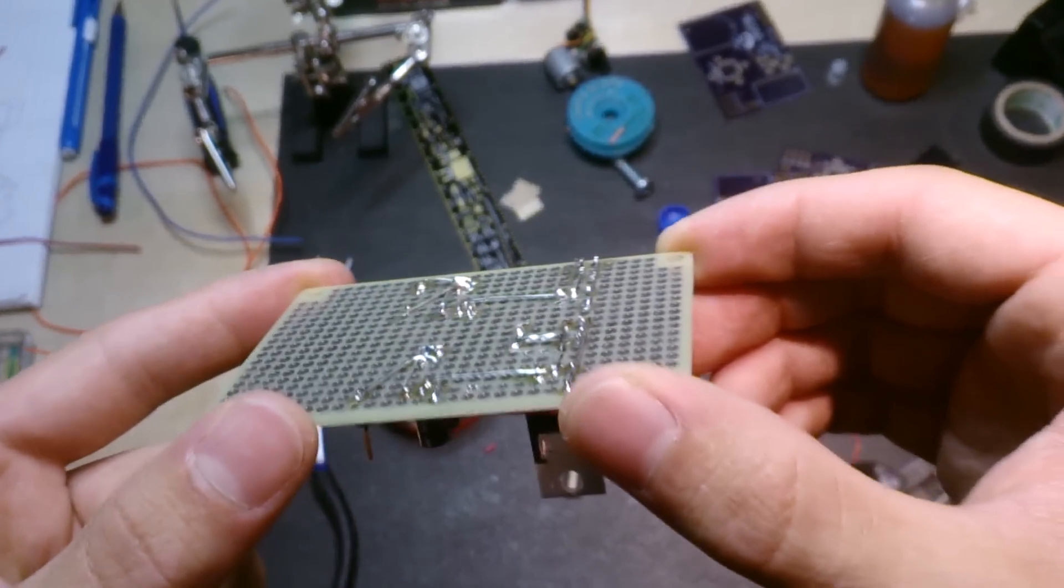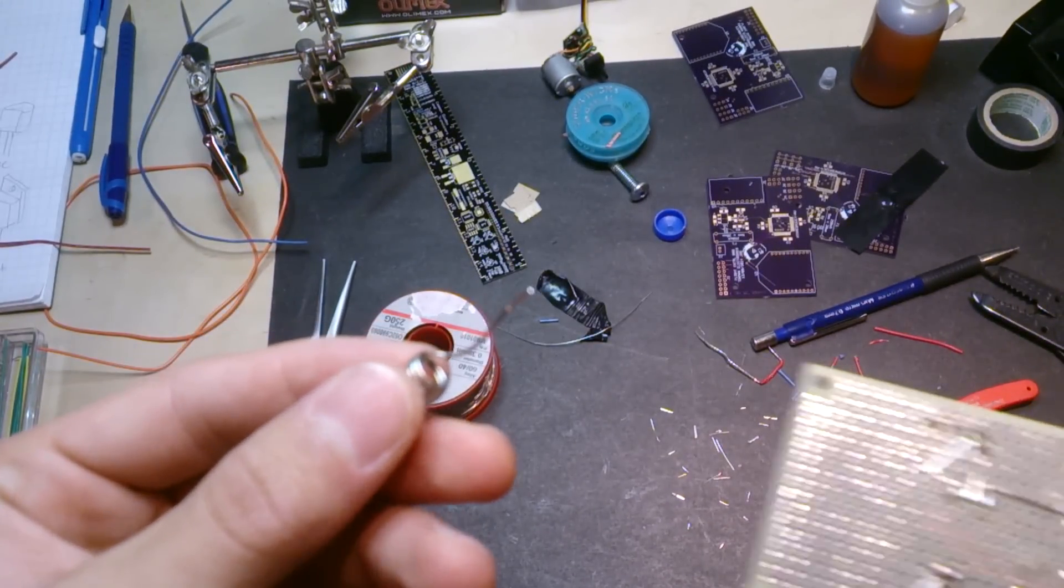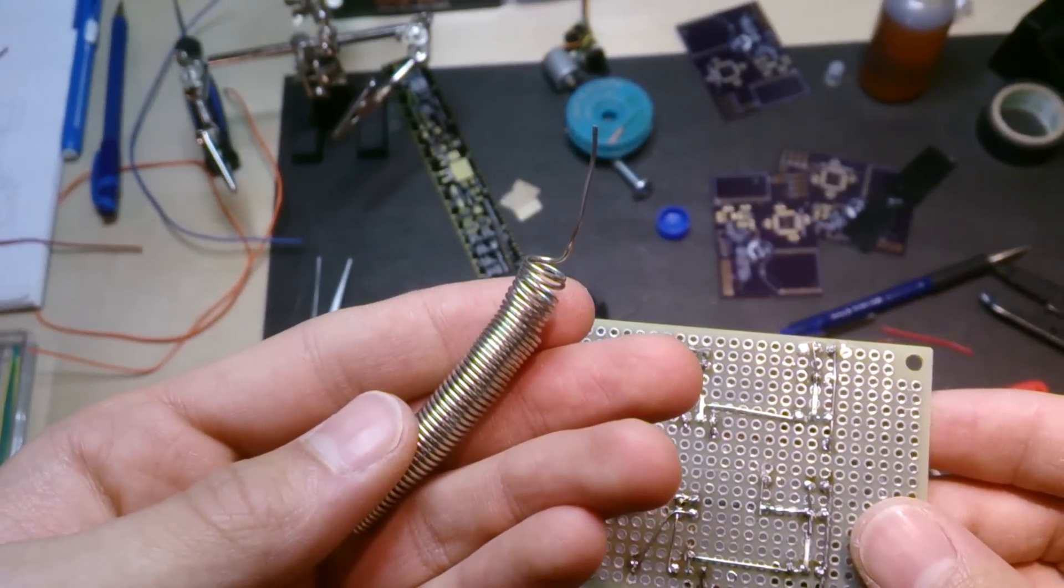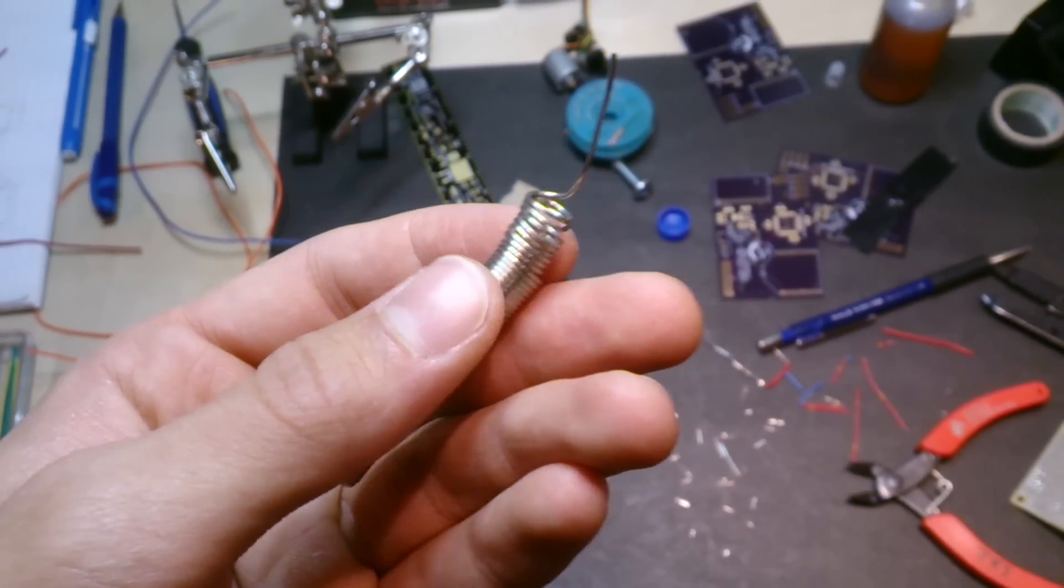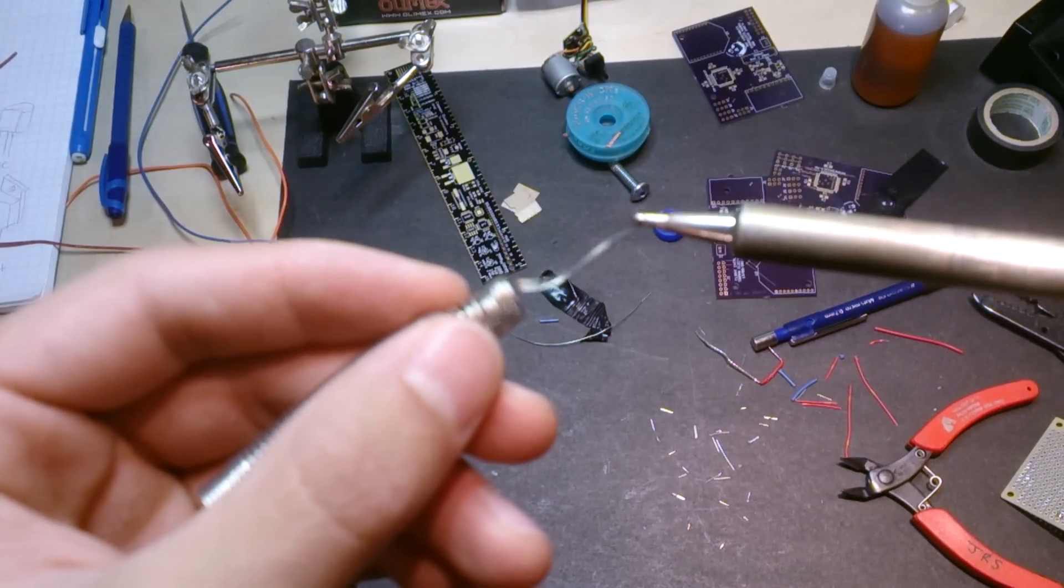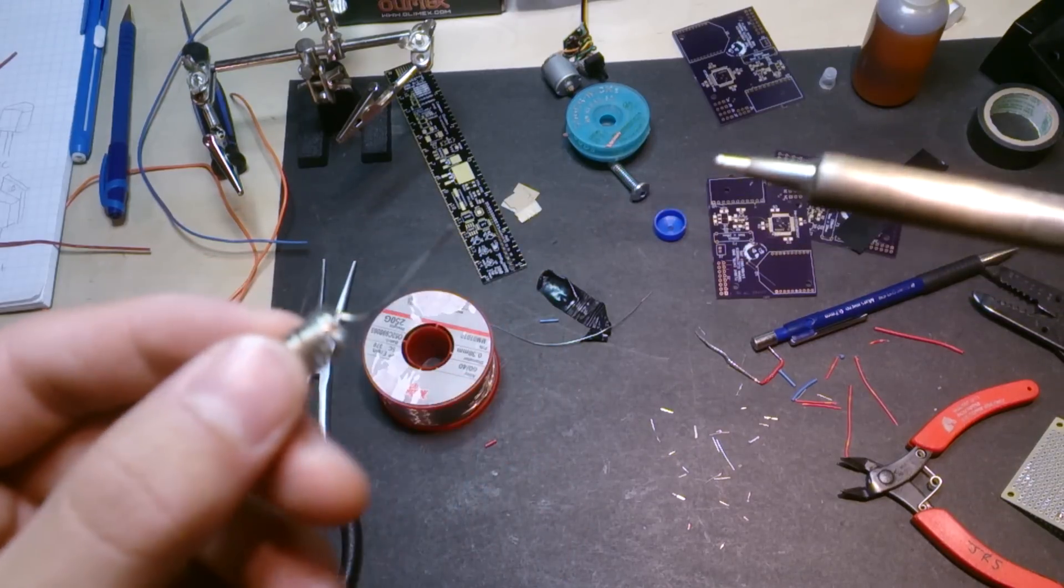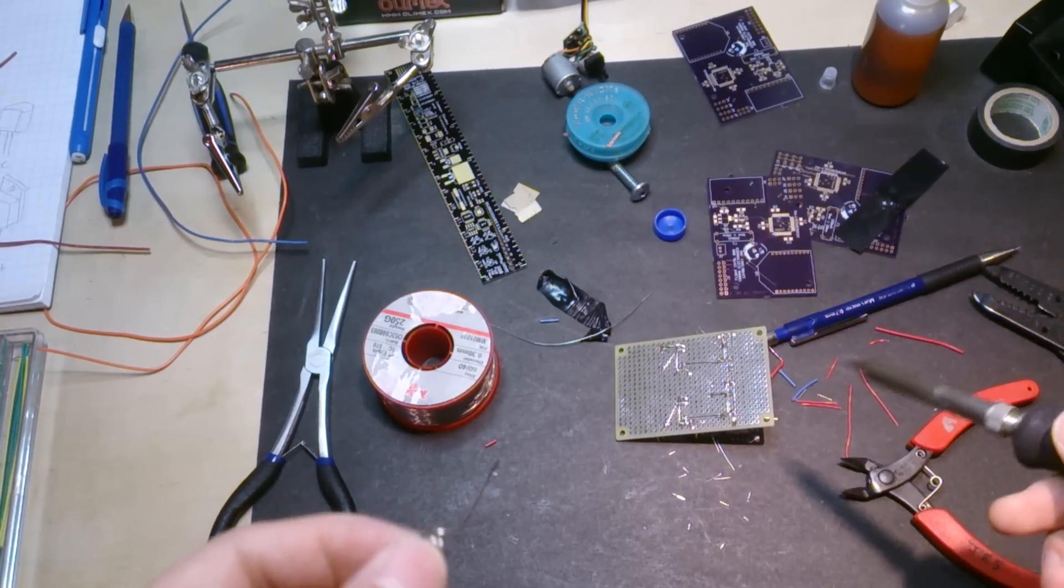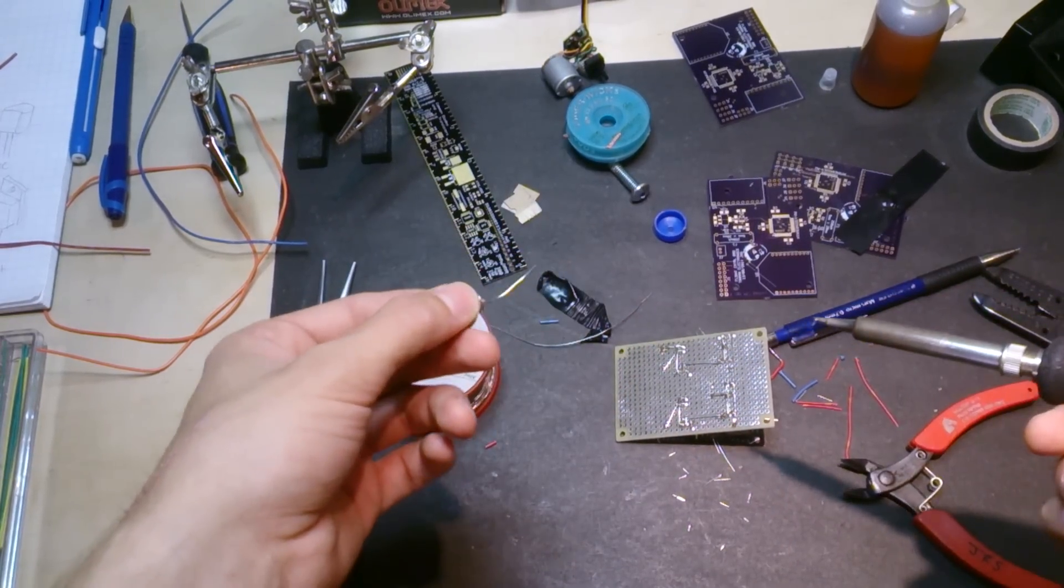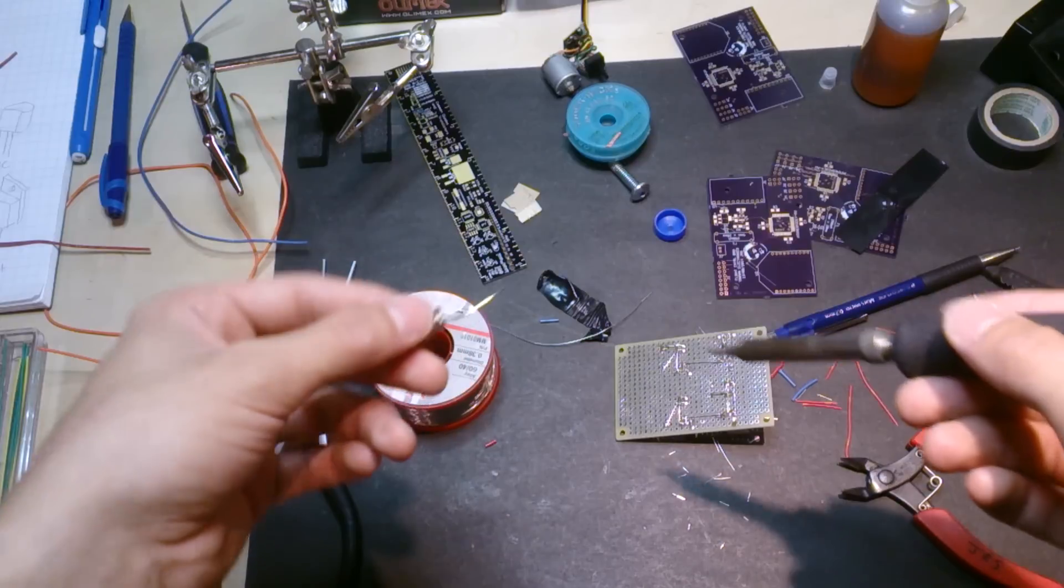I'm gonna take some pictures of this so you can kind of follow along, but as I was putting on the lead-free solder I found it was stickier. Like it did not reflow as easily. I had to bump up the temperature up to like 760 degrees Fahrenheit and even then it was still sticking. Like I would apply my iron to it and it would just not melt. It would take like a split second before it would start melting right onto the iron or tinning the tip, and then I put it onto the circuit and it would take longer for it to melt onto the circuit as well. So it was a little tougher to work with in that sense but it was manageable, so it's not that bad in that respect.